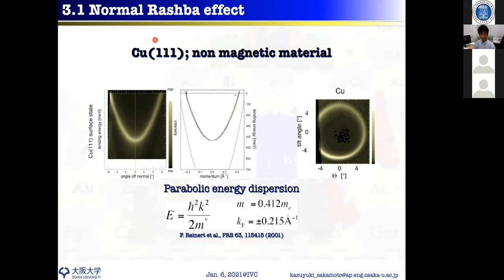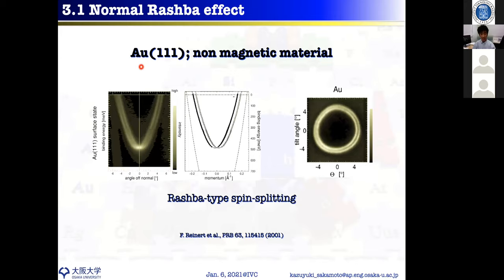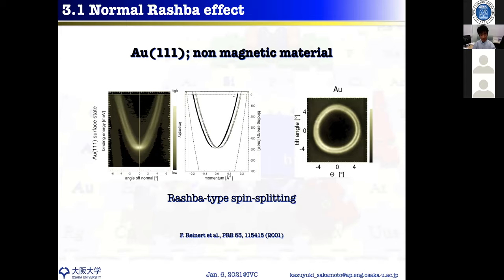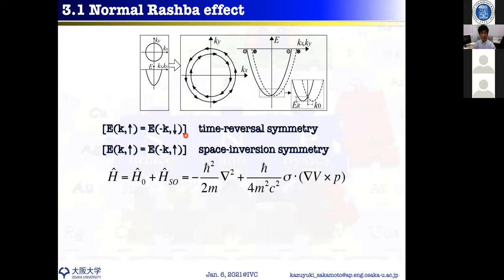For a real crystal structure with atomic layer materials on the surface, we have periodic structures with various symmetries. In our group, we focus on how symmetry modifies the Rashba effect. For example, on a surface belonging to the p3m1 plane group with C₃ symmetry at the K point and a mirror plane rotated 30 degrees from the unit cell, we observe a band splitting — but the splitting is in the energy direction rather than the momentum direction, unlike normal Rashba splitting. The spins also show out-of-plane components due to circular electron motion induced by C₃ symmetry creating an in-plane magnetic field.